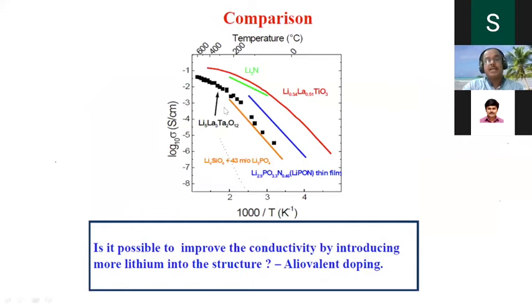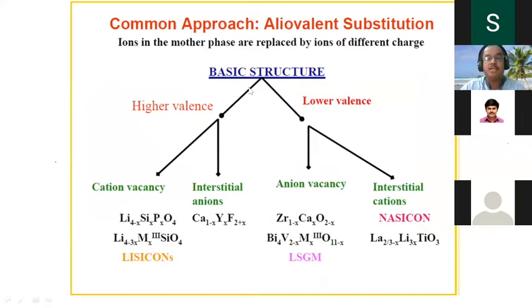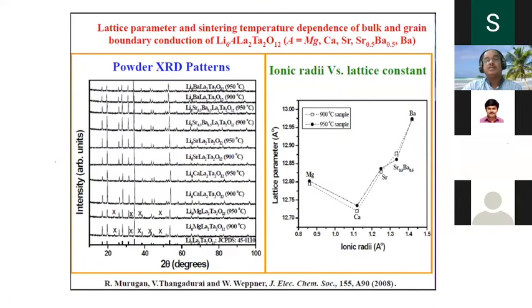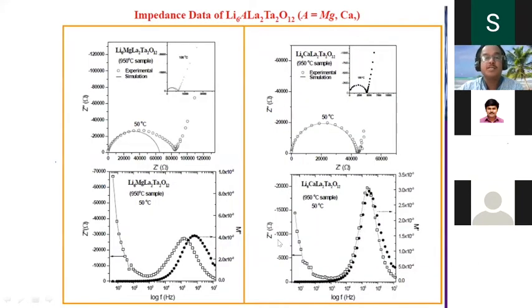So what I did: Li5La3Ta2O12. I considered four; initially we discussed the four best possible combinations. This Li5 comes next, but I still have three more. So I had to cross the barrier, if at all, to realize I wanted to make these materials. What we did was reduce the lanthanum, put in a divalent material, and increase the concentration of lithium to 6. That's why magnesium, calcium, strontium, barium; I could get the best conductivity with the barium substituted system.